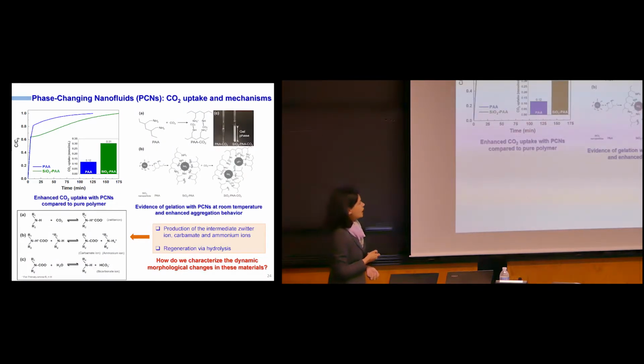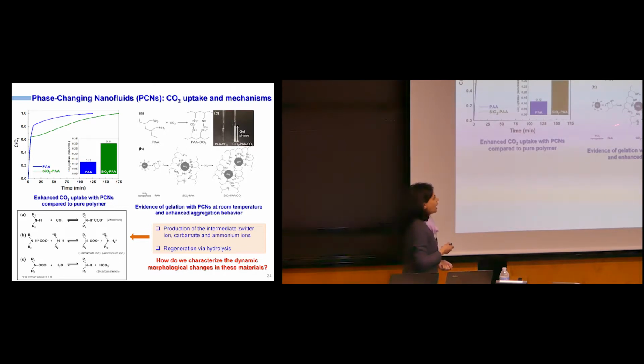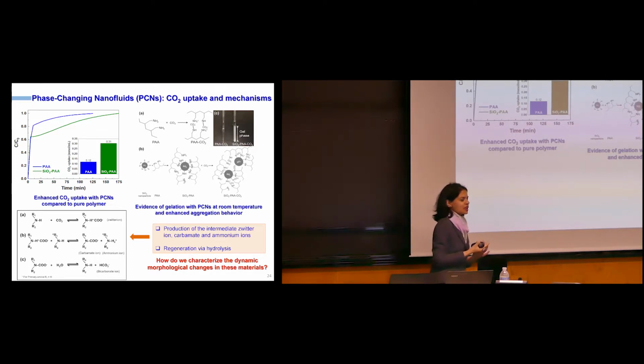So what we did was we have a silicon nanoparticle, and we did not extensively functionalize it, but basically when we have this in the presence of polyallylamines, these polyallylamine molecules tend to organize themselves using hydrogen bonds. And what happens is that in the presence of these SiO2 particles with PAA, you actually have enhanced gel formation. So the way these molecules cause fractures is through hydrogel formation. In the presence of CO2, they form hydrogels. If you have higher pressures, higher temperatures, more extensive formation of hydrogels, they go in, induce higher mechanical strength, cause rocks to fracture, if you like.